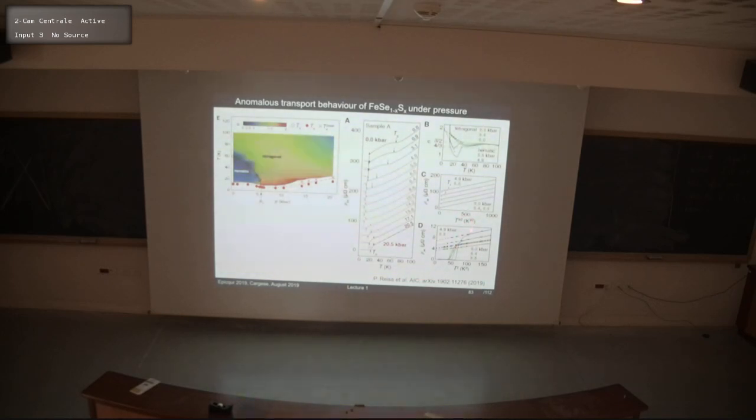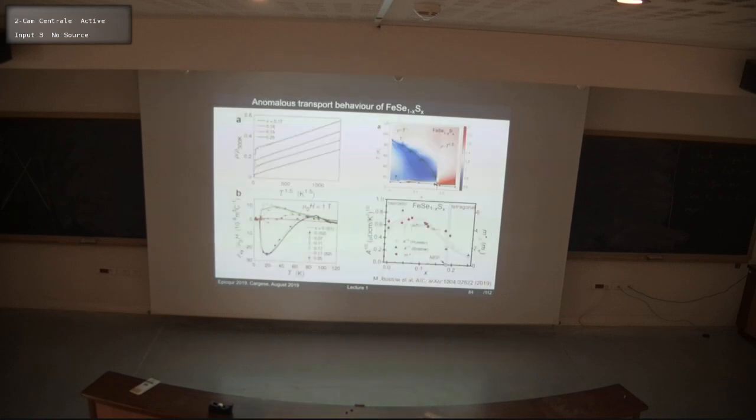So this is quite different to the case where you have antiferromagnetic fluctuations present compared with only nematic fluctuations. So it's likely to be a different type of behavior. And also, if you look at how the exponent varies with temperature in this regime, indeed this exponent stays close to 1.5 in what should be a critical regime.